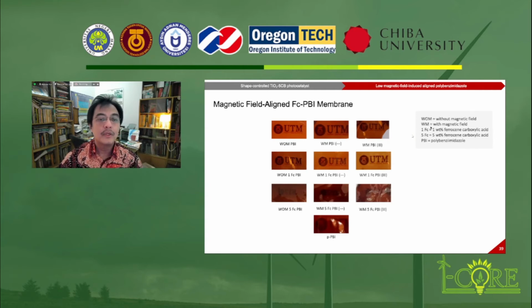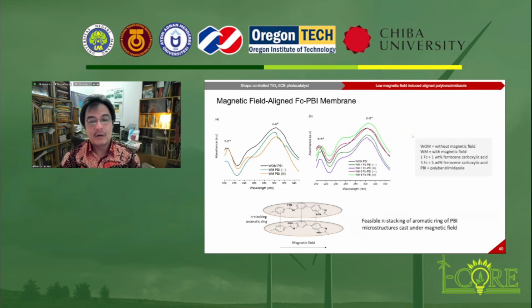Okay, this is WOM, without magnetic field, and WM is with magnetic field. The feasible pi stacking of the aromatic ring, because we know that polybenzimidazole has a lot of polyaromatic rings in the structure. The pi stacking of the aromatic ring of the polybenzimidazole microstructure cast under a magnetic field is demonstrated in this slide.